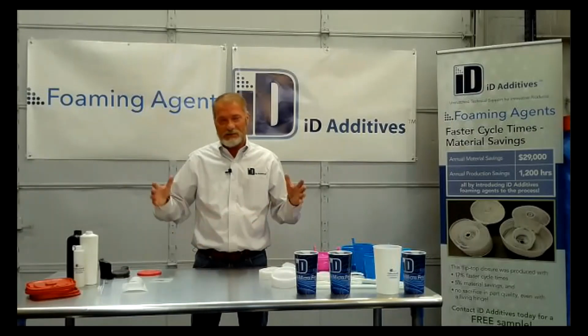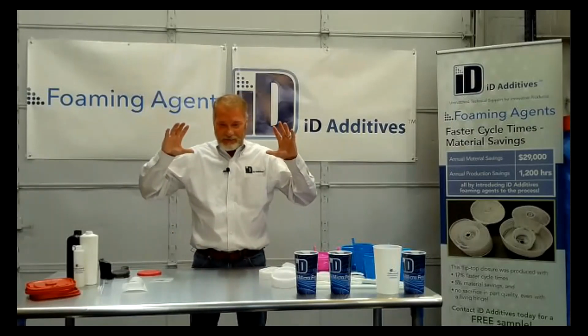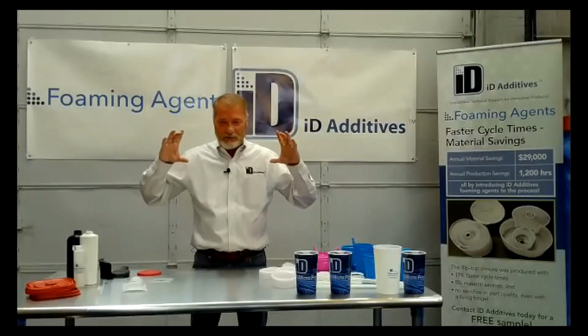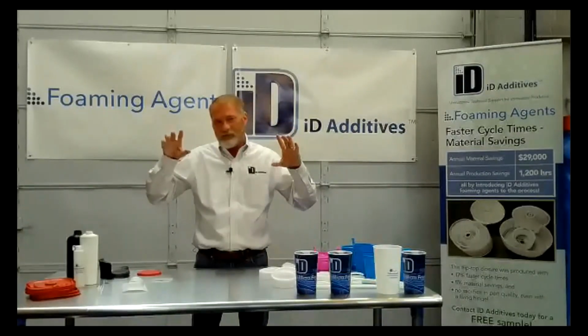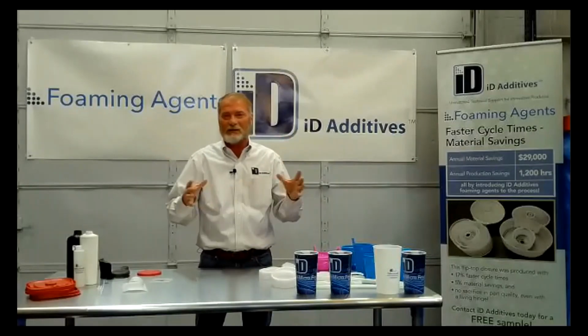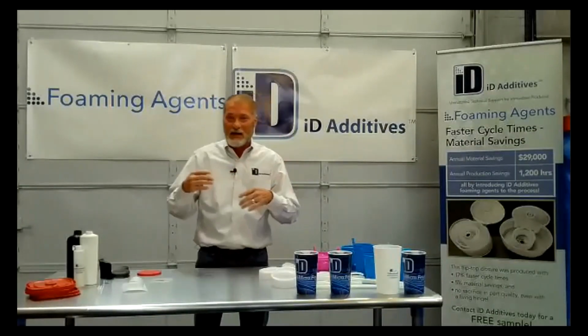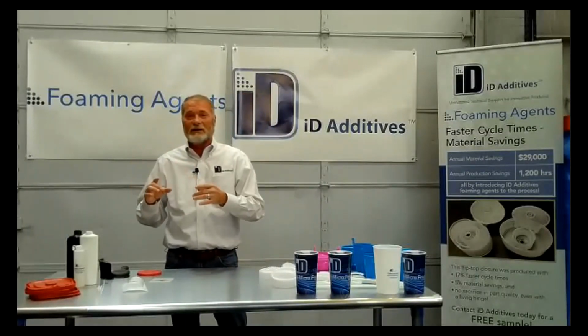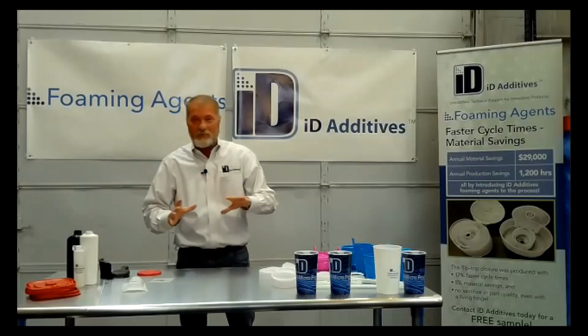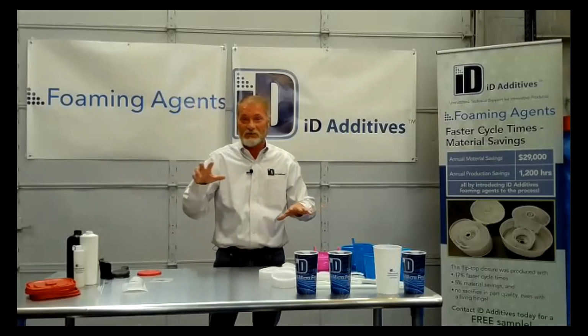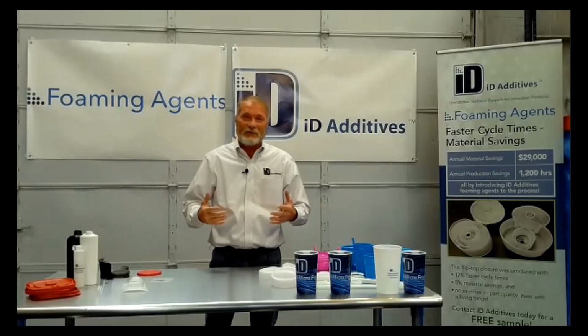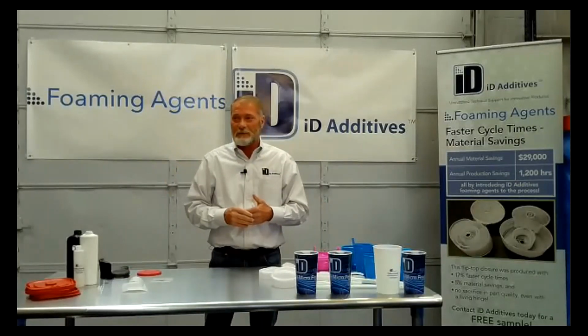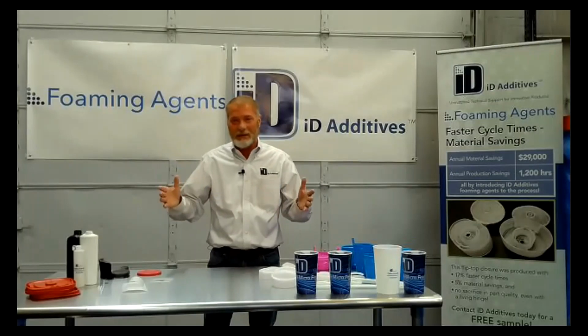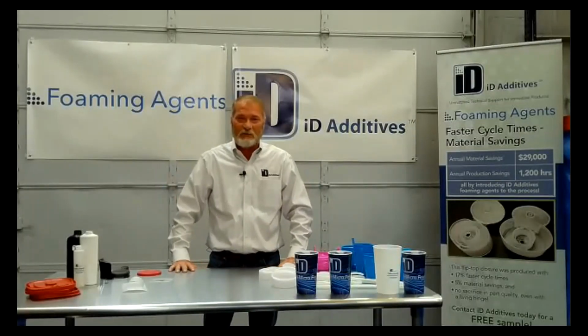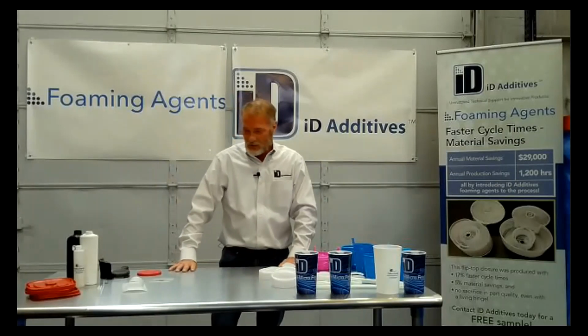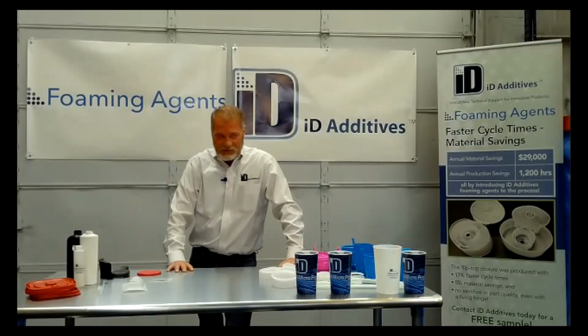But with multi-cavitation, you've got to think, let's say you've got an 8-cavity tool and 2 parts that aren't filling very well, but the 6 cavities were filling like a dream. You're getting all this foam in the 6 cavities, and you're getting foam in the short ones too. But when you start filling those short ones, you start overpacking the 6 other ones. You can manipulate that with tip heats. You can get around that, but again, balance is really important when it comes to foaming agent and injection molding. So we'll step over to extrusion a little bit.